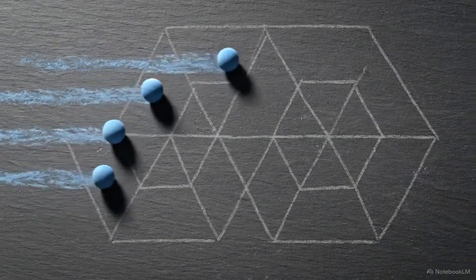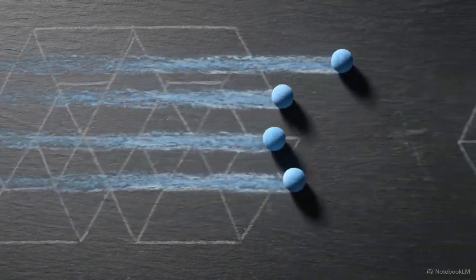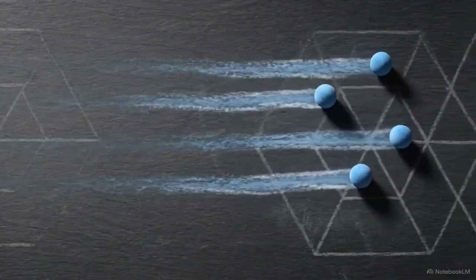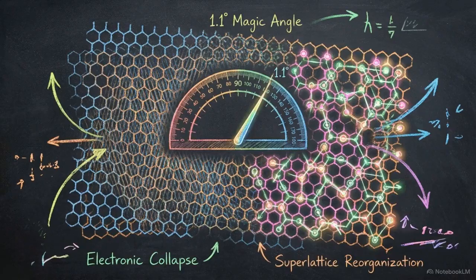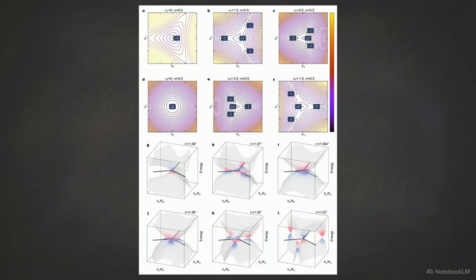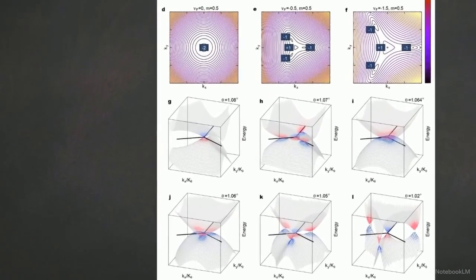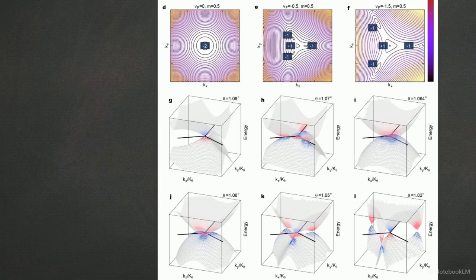At most twist angles, the stacked sheets behave like a standard metal. Electrons flow through the layers with high conductivity. But at precisely 1.1 degrees, the theoretically predicted magic angle, the graphene's electronic properties collapse and reorganize. These 3D energy pathways, or Dirac cones, perfectly hybridize at the magic angle. The Fermi velocity at these points drops to zero. The steep energy slopes of normal graphene flatten into these flat bands, trapping the electrons and quenching their kinetic energy.